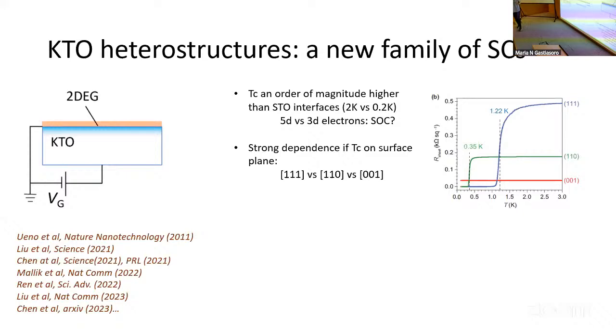And surprisingly, this got a lot of people making these materials. Surprisingly, TC went up a factor of 10. And we still don't really know why, to be honest. The main difference, depending on what material you put, is that the spin orbit coupling goes up a lot, definitely. So maybe having 5D electrons versus 3D electrons could explain this.